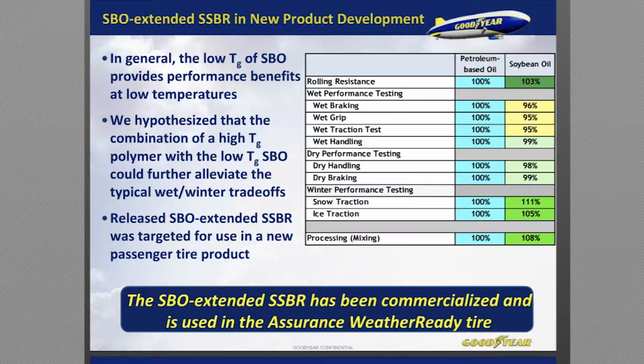The reason why high-performance summer tires perform so well in the summer on your sports cars and things like that is that they're very soft compounds. But those soft compounds have a very high glass transition temperature, so in the wintertime when it gets cold, that rubber gets hard and brittle. It's not as pliable, and you don't get your winter traction. Here we were able to achieve both simultaneously, and we were able to use our released soybean oil extended polymer in the Assurance WeatherReady tire.